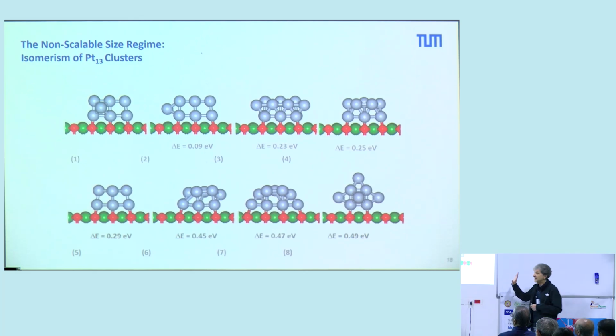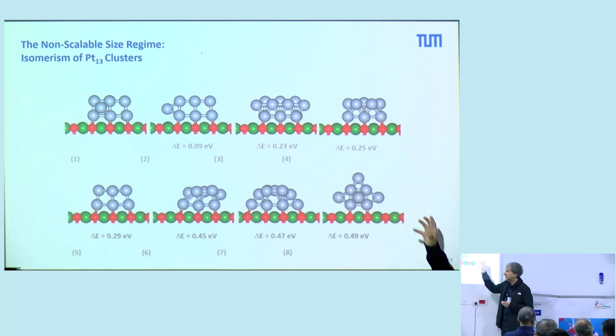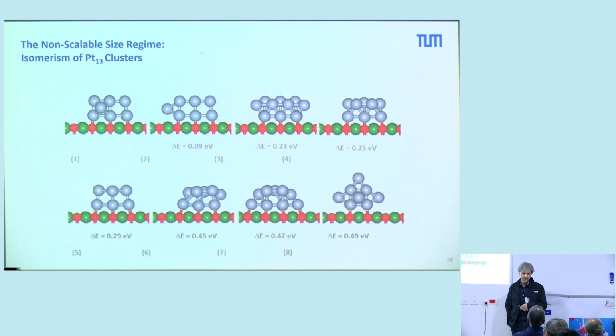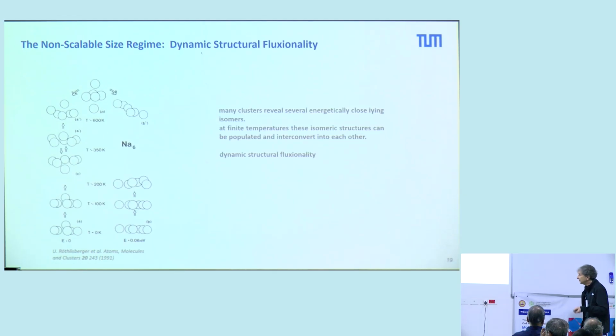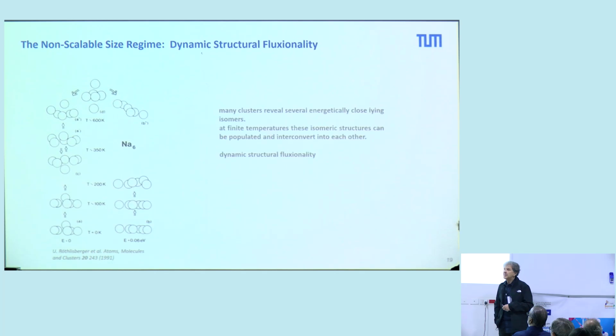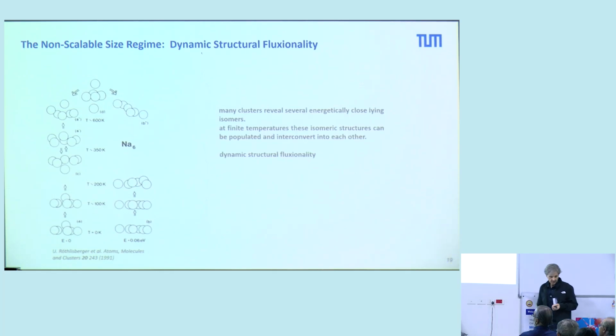That means at finite temperature, you always have a Boltzmann distribution of these different structures. And each isomer can have a different chemical property. So you have to be aware that when you talk about size effects, it can also be simply a question of an isomer. And they can interconvert into each other at finite temperatures, and this we call dynamic structural fluxionality, because along a reaction, they can change the structure. And we believe that this is a key for the low temperature catalysis we observe for these very small clusters.